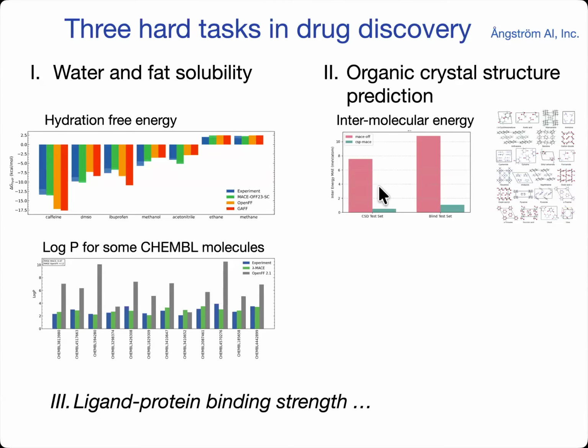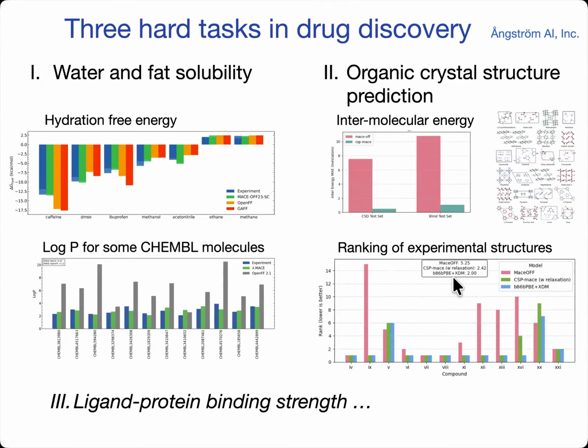small errors. The left side is a test set on the Cambridge Structural Database, so a large experimental test set. And on the right, I show the test set on drug type compounds from the blind tests over the years. People set up a challenge to predict drug crystal structures. And for these blind tests, we can also see if we get the lowest energy structure to be the one that they see in experiment. And here, the baseline is DFT. It's expensive, but this is how people do it. This is how drug companies try to predict the stability of the crystals of new compounds. And this is a particular flavor of DFT that does reasonably well.